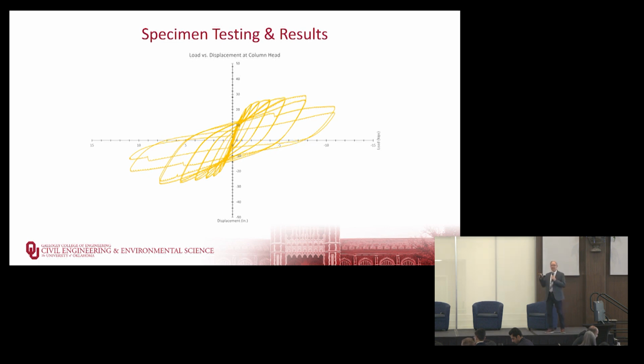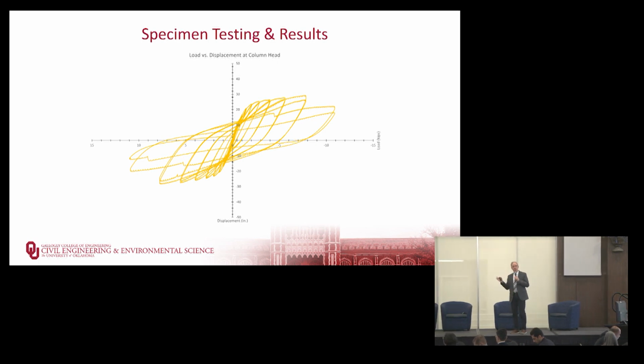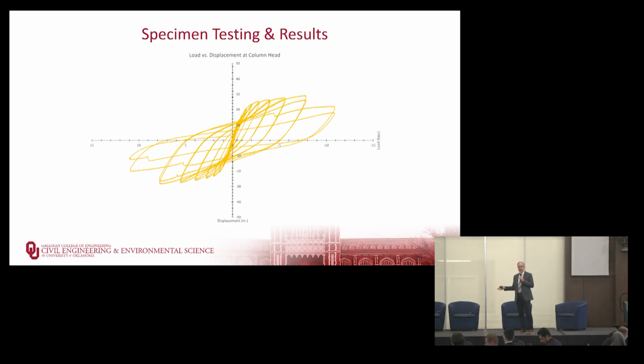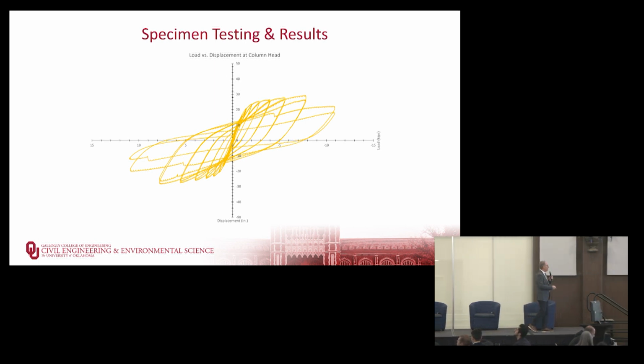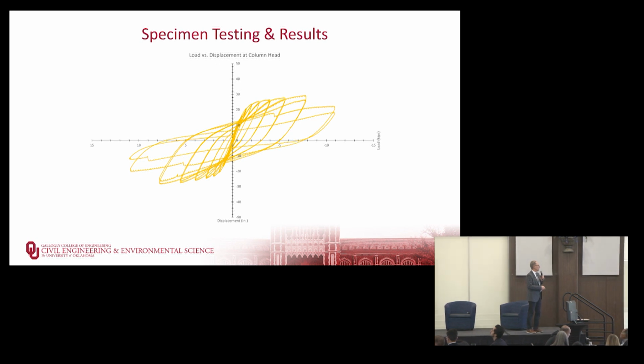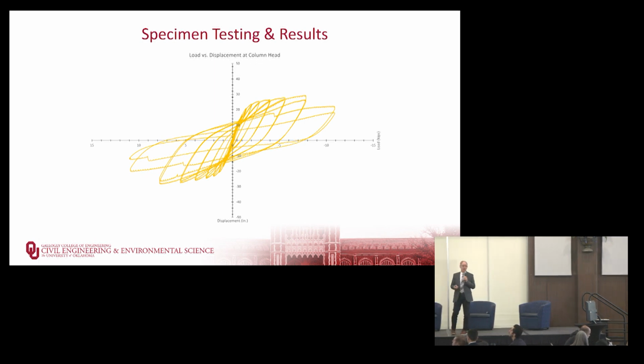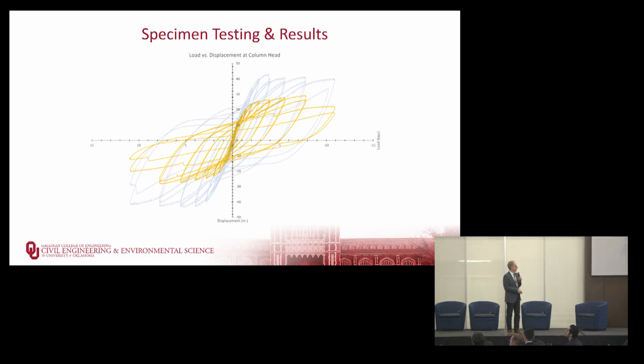So this is an 8-foot tall column that we wanted to push a foot in each direction. So that in one direction, that's a drift ratio of 12.5%, which is huge, right? An 8-foot tall column moving a foot. If you saw that in a bridge, that would be kind of scary. We push it all the way up to 1 foot in both directions for the peak response. And we compared this with research on reinforced concrete columns. The behavior was very typical. So we felt like our test frame of loading, turning the column on its side and testing it, worked very well. So we were ready to test our innovative columns.